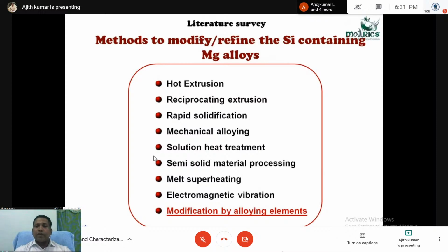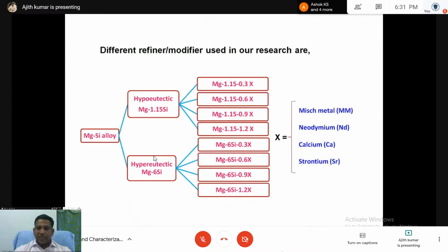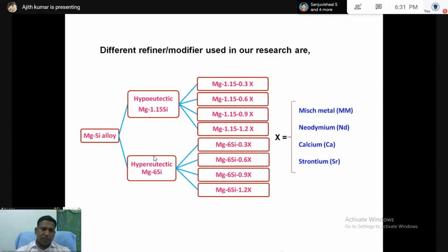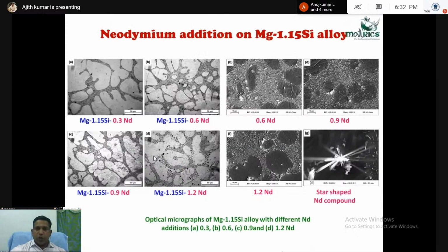So one of the important modification methods is modification by alloying elements. In our thesis, we chose four different elements: mischmetal, neodymium, calcium, and strontium. We checked these four elements in two different alloys, that is, one is Mg-1.15Si alloy and another one is Mg-6Si alloy. So by the addition of these elements, we analyzed how the microstructural changes come and what the reason is. I'm just showing only one addition, that is neodymium addition.